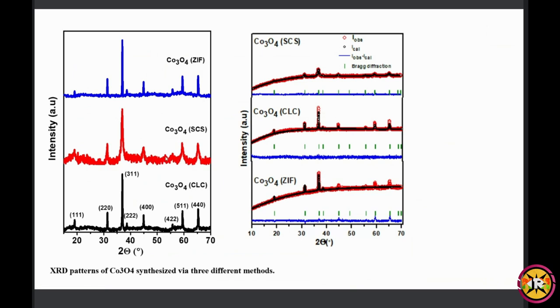I have calculated the crystallite size by using the Scherrer equation, that is, D equal to 0.89 lambda over beta cos theta, where lambda is the wavelength of the X-ray, beta is the full width at half maximum, and theta is the corresponding angle. So from here I have observed for Co3O4 SCS, the crystallite size is 14.02 nanometer, whereas in case of ZIF and CLC it is 76 and 89. So it's quite higher. So from here also I can conclude the crystallinity of Co3O4 SCS is less than the other two.